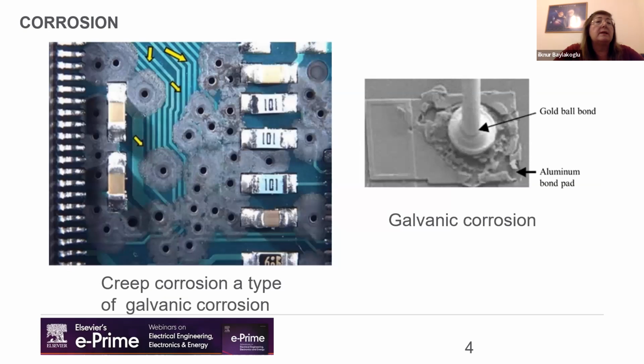And what can be these failure mechanisms caused by water? One of the most famous ones is corrosion. It is a very known failure. Actually, it is a very widely seen phenomenon, and it is caused by water in its different forms. Corrosion is a reaction of a material with its environment. In general, corrosion is causing failure modes which are irreversible. When there is a mechanism caused by moisture, a corrosion mechanism, it is an electrochemical process. It can be a galvanic corrosion or it can be a creep corrosion.